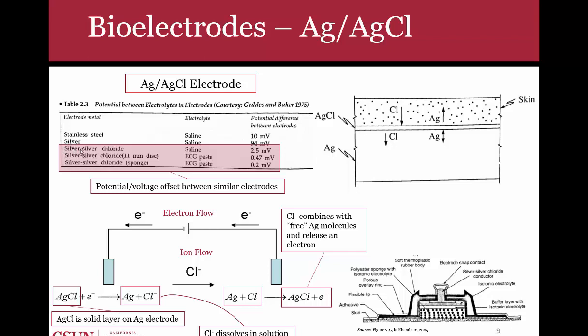And there's other ones called silver chloride electrodes. Alright, so I highlighted silver chloride for this reason. The first reason being that you see that the difference between electrodes is actually very small. So what does this mean? You have one silver electrode and one silver chloride electrode, and that produces a 2.5 millivolt difference, which is very, very small. And if you use a sponge, you can even get much smaller voltages. So how does a silver chloride electrode work?